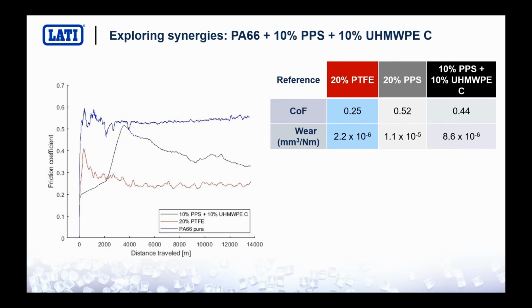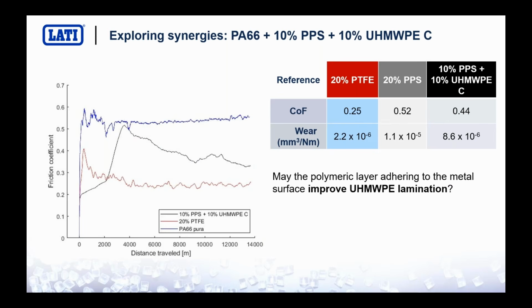Then we started to analyze some synergistic effects, for example between PPS and ultra-high molecular weight polyethylene. And here you can see the results. The aim was to help this kind of lamination of ultra-high molecular weight polyethylene, like what happens for PTFE, in order to favor the film transmission. Small improvements were detected on both wear and friction factor, above all if we compare with the version with only PPS. So it seems that the behavior of these two additives together is better than the material with only PPS, slightly better in both properties, friction coefficient but also wear.